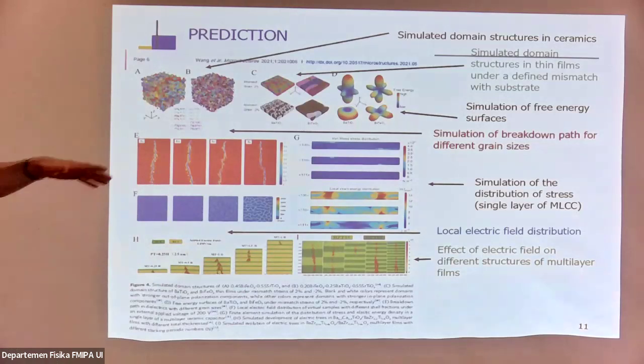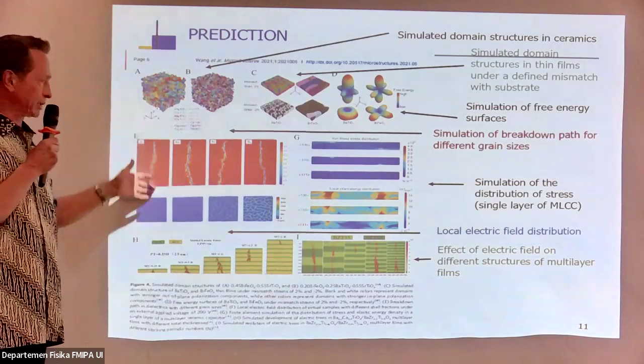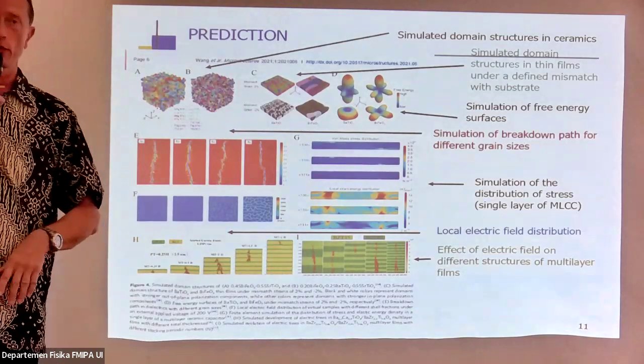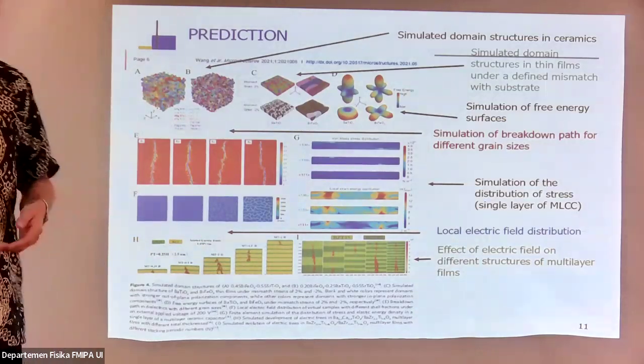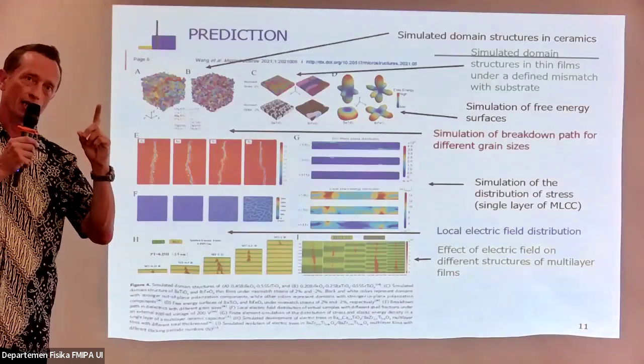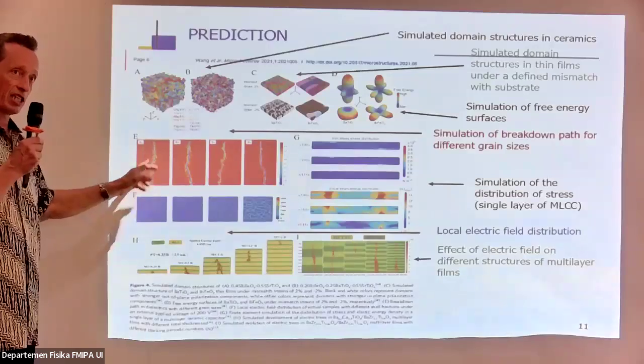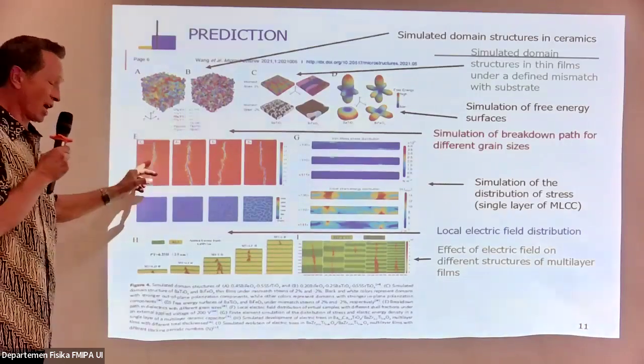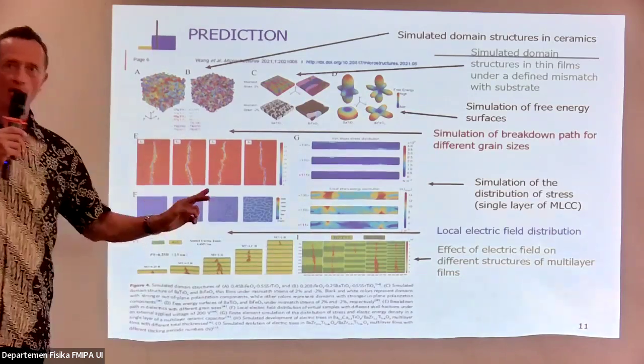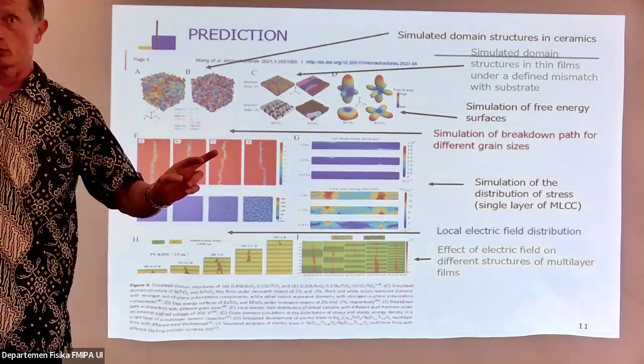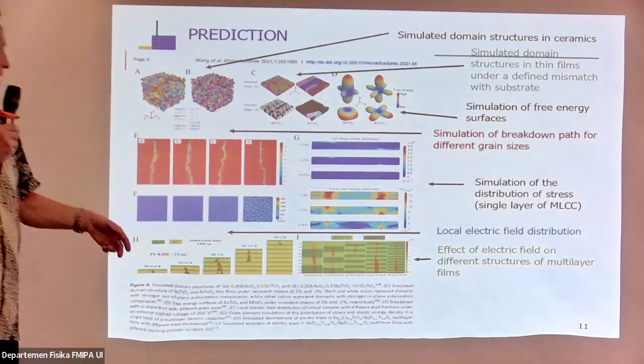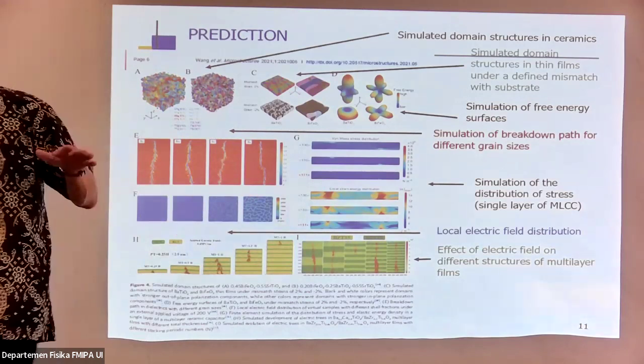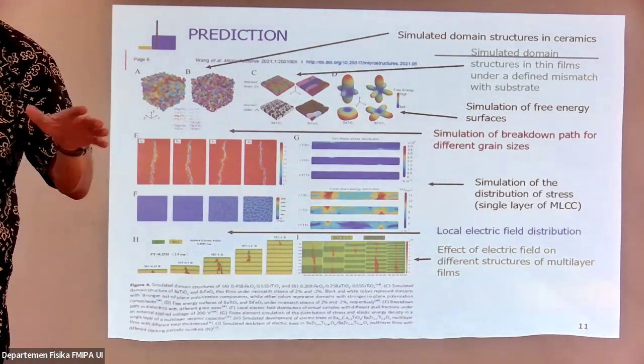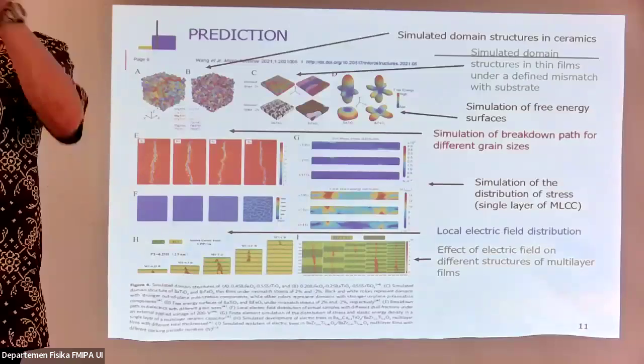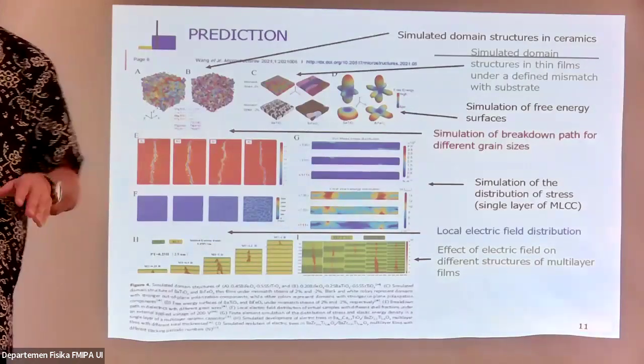But to increase the voltage, you have to solve a big problem with high voltage, which is the possibility of breaking down your material. We talk about electrical breakdown. And you have to develop the resistance of your material. That means your material should resist being broken by the maximum applied electric field resulting from the application of high voltage. When you have a breakdown, your material is destroyed. It's not a reversible process. If you have a breakdown somewhere, it's finished. The equipment, your material, is destroyed.